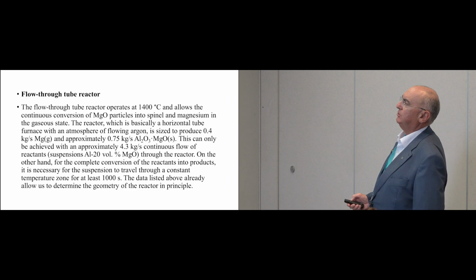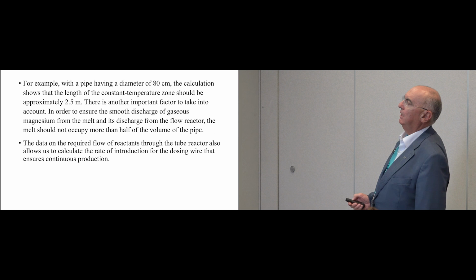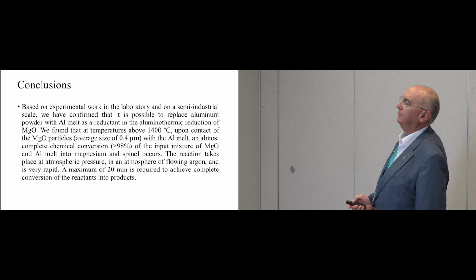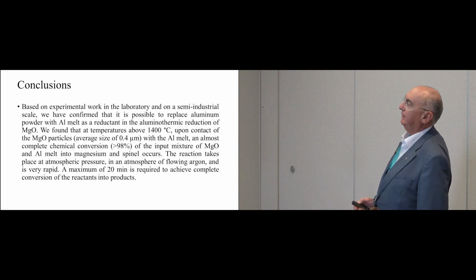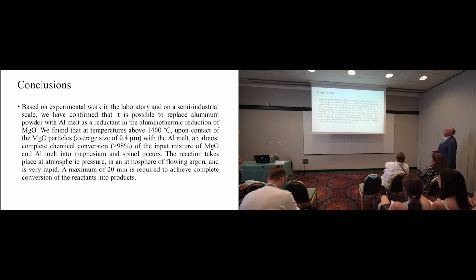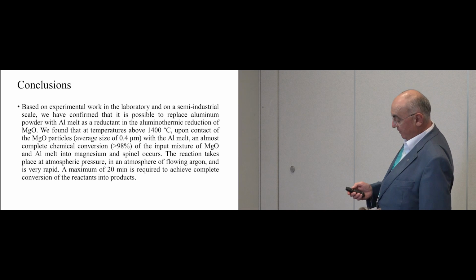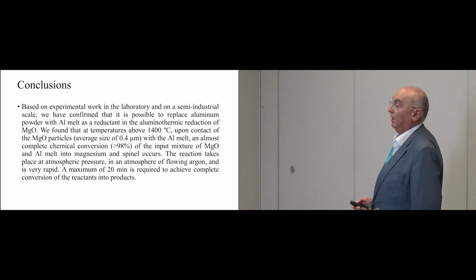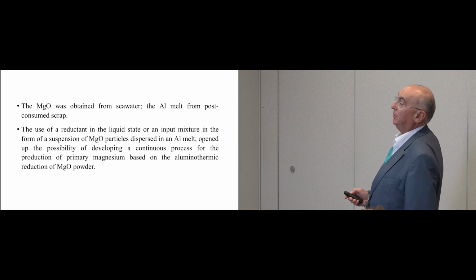Okay, this is the description of some of those units. There is no time for that, but based on experimental work in the laboratory and on a semi-industrial scale, we have confirmed that it is possible to replace aluminum powder with aluminum melt. We found that at temperatures above 1,400 degrees, we get almost complete chemical conversion. The reaction takes place at atmospheric pressure in an atmosphere of flowing argon. It's very rapid. In 10-20 minutes, you can achieve high conversion of the reactants into products.